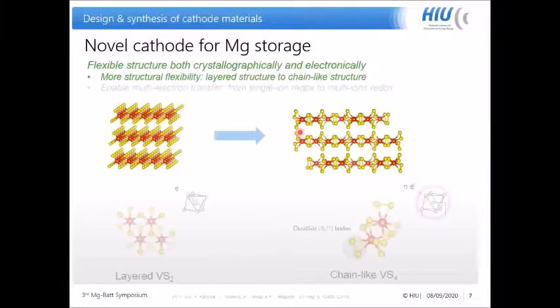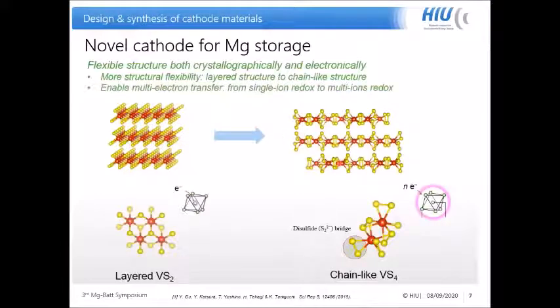On the other hand, in order to enable this multi-electron transfer, we are thinking to involve anions in the redox process, so that we have this electron cloud over the whole cluster, which could take the multi-electron transfer. That's why we chose vanadium tetrasulfide as a model material and studied the magnesium storage capability in this cathode. The reason is that the atomic energy levels of vanadium and sulfur are close to each other.